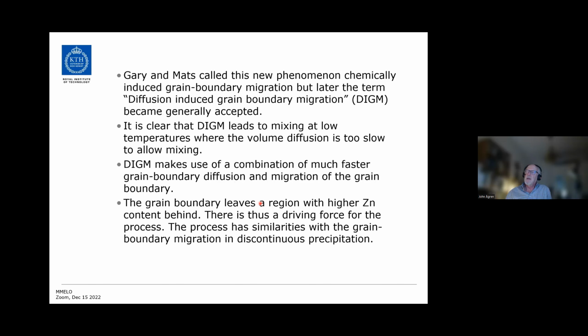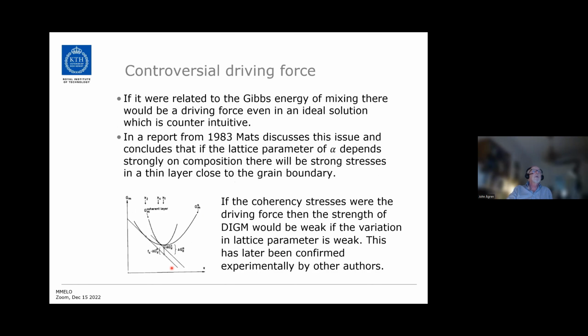So DIGM makes use of the high diffusivity in the grain boundary and the relatively high grain boundary mobility. So this grain boundary leaves a region with higher zinc content behind. Well, there is a driving force for the process. But this driving force was really controversial.